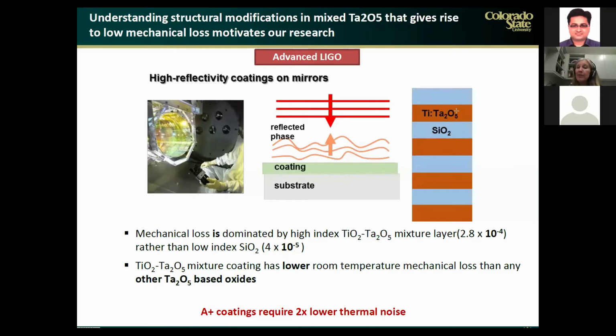Now, experiments have shown that it is the high index layer that has the highest mechanical loss at room temperature. So this is exactly the material that we have been studying with the goal to understand the origin of this internal friction and to develop new materials that will have lower internal friction. We have a goal to decrease mechanical loss by a factor of 2. We should have had this material already had it not been for COVID, for A+, which is the next generation of gravitational wave interferometers.